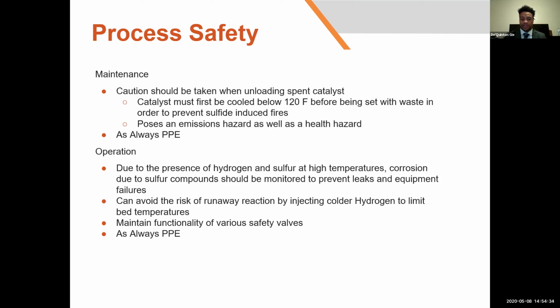And then for operation, due to the presence of hydrogen and sulfur at high temperatures, corrosion is very possible. And we chose to inject colder hydrogen into our reactor in order to prevent a runaway. That way, it makes it less of a risk of happening.